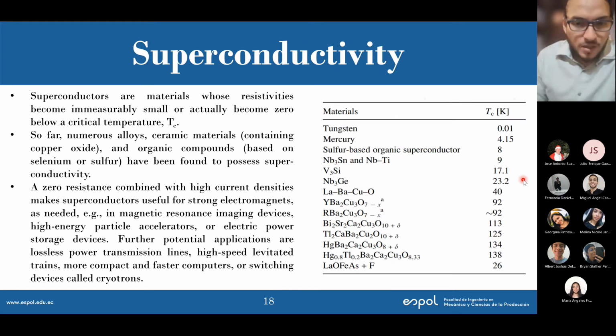Superconductivity. Superconductors are those materials whose resistivities become immeasurably small, so that one can consider them as zero, once we get below a critical temperature. The problem with that critical temperature is that it's usually quite close to 0 Kelvin, to the absolute zero, right? And we all know that it's quite difficult to get there. But that's actually what superconductivity is. Superconductors are called that because they basically have zero resistivity below that critical temperature. Once I go above that critical temperature, superconductivity is lost.